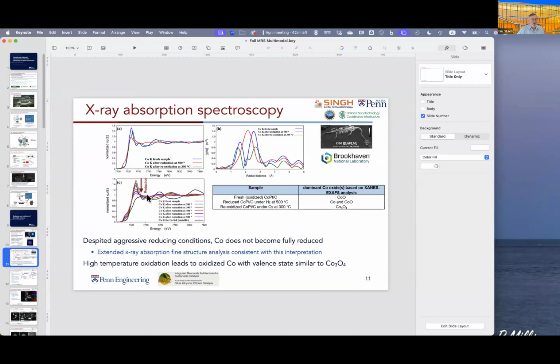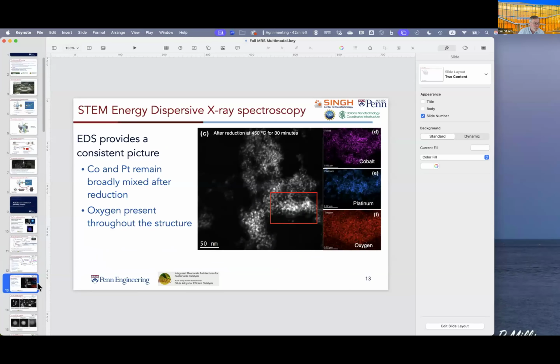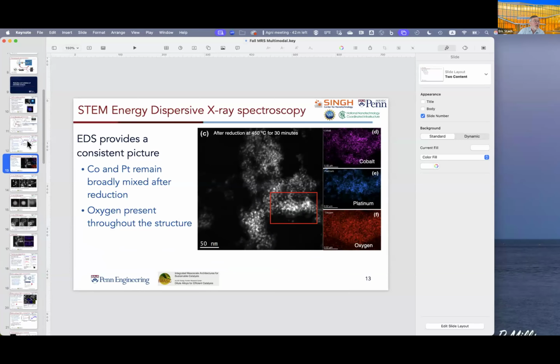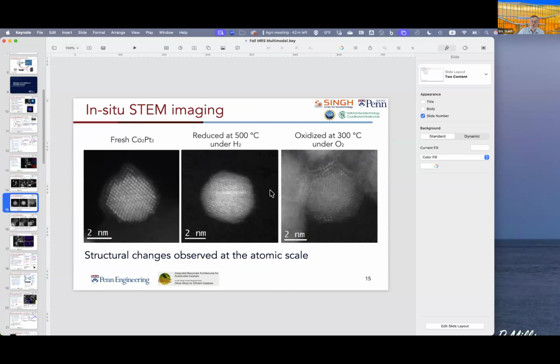To some extent, Nestor, this is one of the nice things about having the dual information: even in the case of the X-ray data, which has no electrons in it at all, you see the same formation of the cobalt oxide. But if we go through and look at things like the EDS and the EELS, where am I? Here's just imaging, right? So again, I think there's no question that you have the formation of this oxide shell here. And that's consistent with the EELS.